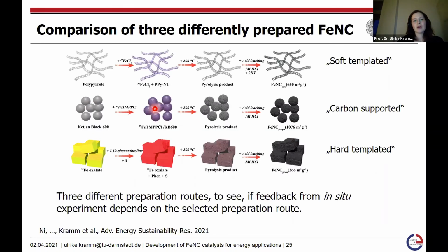In relation to this, we compared three different preparation routes. I would not like to go into too much detail here, but the aim was to understand whether the changes that we might see during in situ Mössbauer spectroscopy are only valid for one type of catalytic system, or whether we can see the same changes for different preparation routes. As these three preparation routes are representative of the three main routes, soft templated, carbon supported, or hard templated, we thought this is probably a good approach to get better insights into to what extent the preparation route might also affect the spectroscopic outcome.